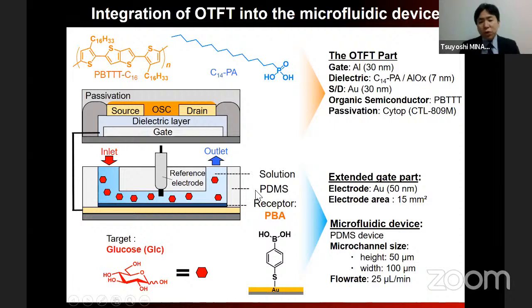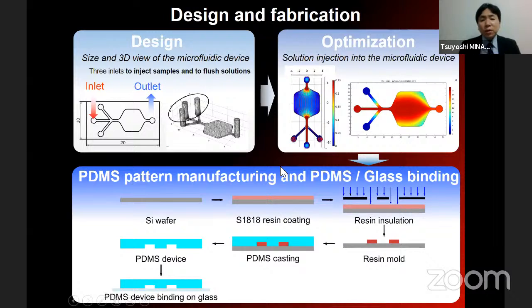On the gate electrode we put the microfluidic chamber system. The height and width are roughly 50 micron and 100 micron. The flow rate is 25 microliter per minute. This is because we want to monitor the activity of cells in the future. So this is the design of the microfluidic system. We also designed it using COMSOL software, which is commercially available software to design microfluidic systems. So here is the inlet and here is the outlet.